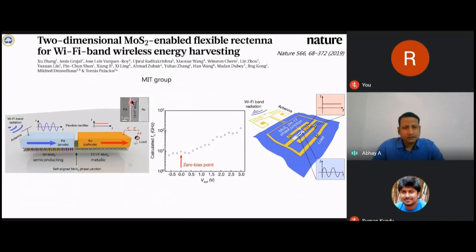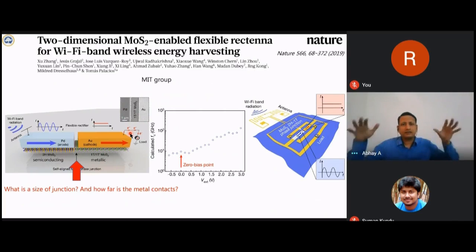So these are the two metal electrodes. One is palladium and the other one is gold, and MoS2 is in between. You can notice the size of the junction which is formed. The junction width is hardly 1 nanometer. But if you look at the scale bar, the separation between the two metal electrodes is between 1 to 2 micrometers. It means a junction of 1 nanometer is collecting charge carriers over a distance almost 1000 times larger than the junction. So they obtained a cutoff frequency in the range of 10 gigahertz.